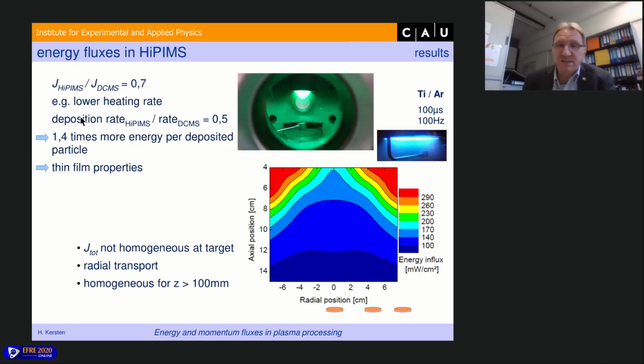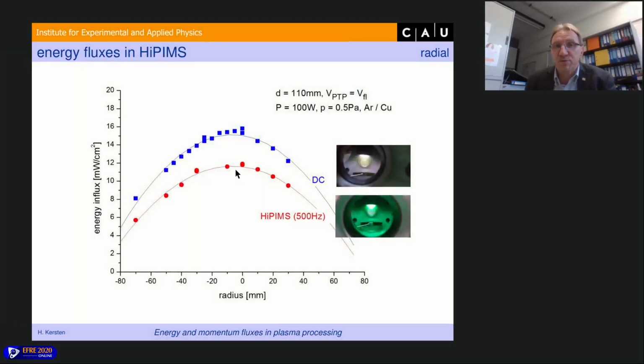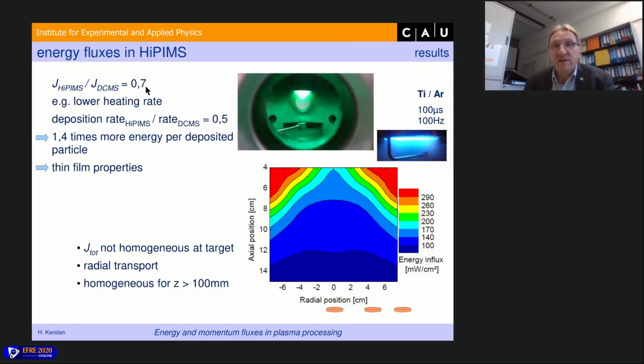Also, due to the pulsed nature of HiPIMS, the deposition rate of HiPIMS sputtering is lower than for DC. In our case, it was about 50%. But the energy flux in the HiPIMS case is 70% of the DC flux. If you divide these by each other, you get 140% energy per deposited particle. So per deposited particle, the incoming energy or deposited power is higher than in the DC case, not on average, but per particle.